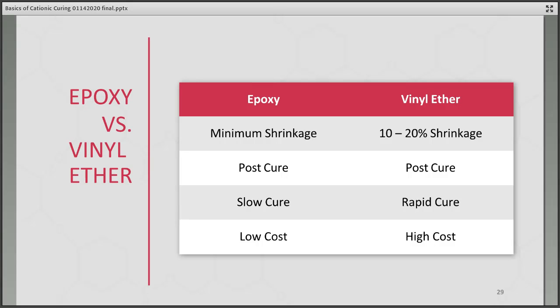But there are some advantages of using vinyl ether that are out there. Let's compare it to epoxy structures. Okay, in an epoxy structure, you get minimum shrinkage because you're ring opening. However, vinyl ethers act more like free radical acrylate, methacrylate systems, and you can get up to 10 to 20% shrinkage. Both epoxy and vinyl ethers post-cure, so you're able to take advantage of that. Where vinyl ethers really shine, and have an advantage, is in their reactivity. So epoxy is relatively slow cure. Vinyl ethers cure very, very fast, so they help speed up your reaction.